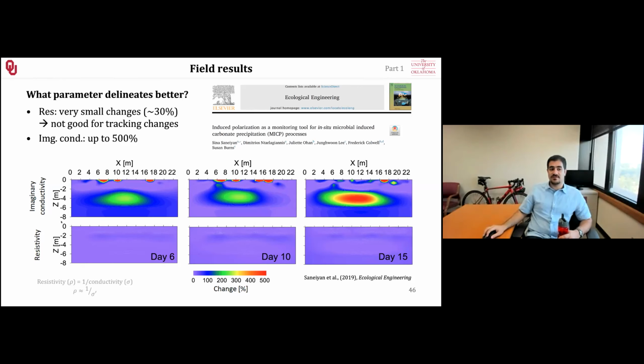But imaginary conductivity, on the other hand, was able to show more than 500% change over time. So it is very sensitive to the precipitation of this fine powdered calcite inside our soil. So this is technically the right method to go with. You need to measure induced polarization to be able to get the imaginary conductivity to measure if your MICP is working. Resistivity alone won't work.